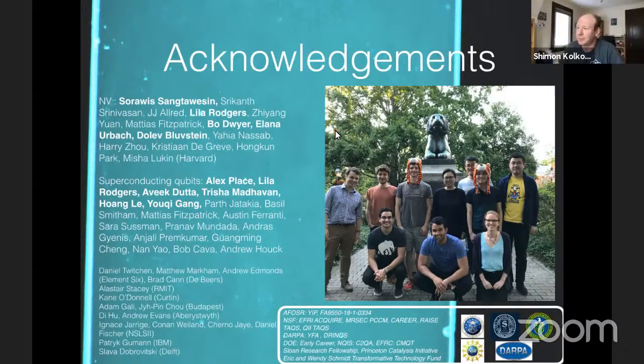Great. We had a question from Aziza. Is the Q limit from loss tangent on top of the superconductor frequency dependent? Does it get worse or better depending on the frequency of the device? No, from what we've been able to see, at least over the narrow range that we look, which is typically between 5 and 7 gigahertz, we don't really see a frequency dependence. When we do see one, it's usually something really annoying, like we've accidentally made a mode in our packaging, and then you're seeing coupling to that mode, but it's easily avoidable.